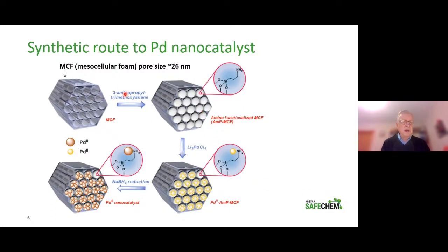Now, nanopalladium catalysis. We are using a mesocellular foam material, which is a silica material, and here you have small cavities which are spherical, connected to each other, and this silica material contains a lot of hydroxy groups. And this 3-aminopropyl trimethoxysilane, which is a 3-carbon unit with an amine, you bind to the hydroxy group of the siliceous material, and there you have the amine as a binding site for metals.